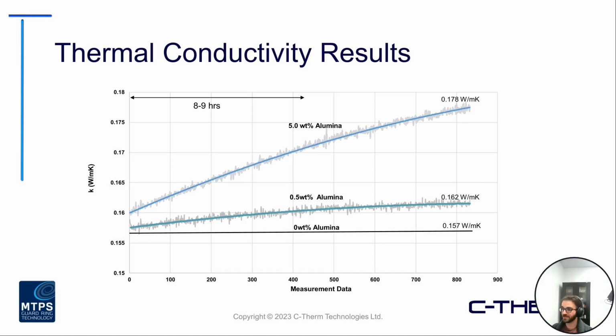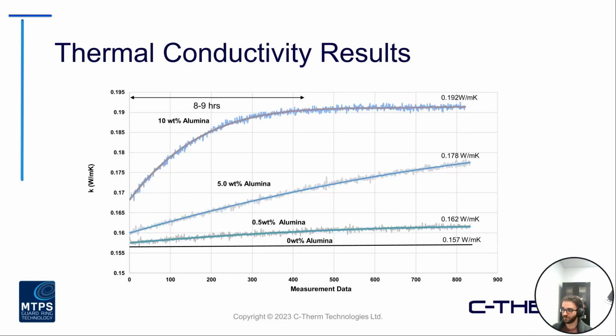And then just following the trend, we looked at the different weight loadings. And of course, as you would expect, not only do the higher weight loadings result in a higher end value, but you can see the trends as that settling is occurring as a function of time. And then finishing off with that highest weight loading there.